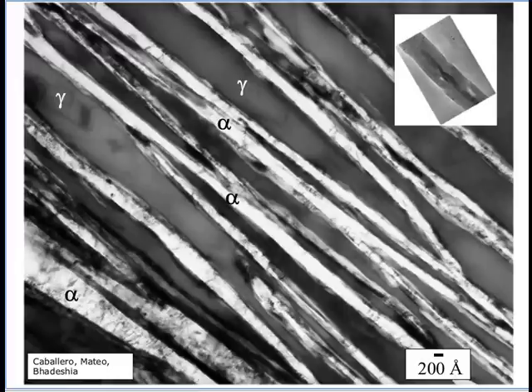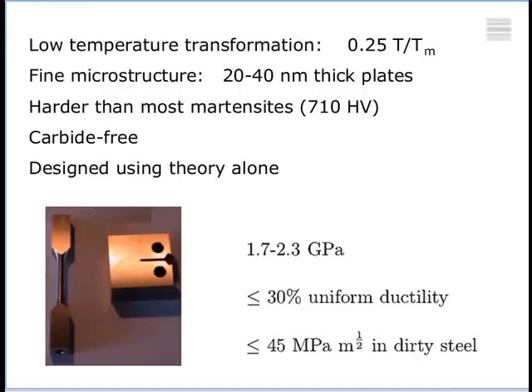I'll talk about ductility shortly. And it's a very, very simple structure. Incredibly fine crystals of bainite in a matrix of carbon-enriched austenite. So this has been produced at the lowest temperature ever for bainite, about 200 degrees centigrade, a fine microstructure which is finer than carbon nanotubes, extremely hard, 700 Vickers, there are no carbides, and these are the properties.